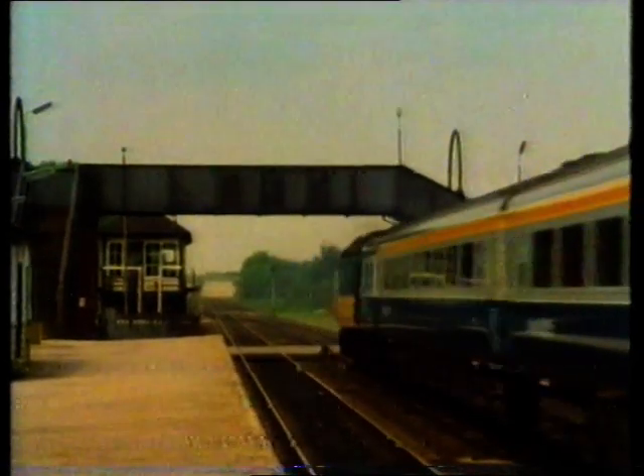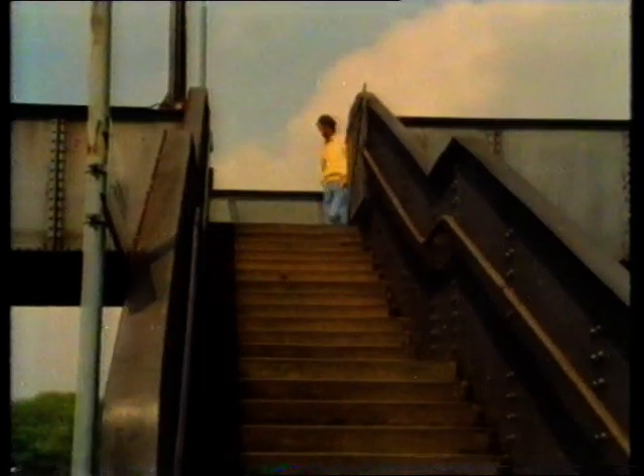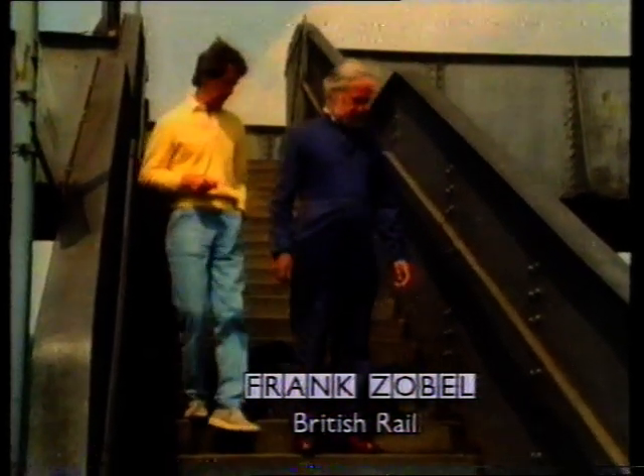And British Rail owns huge numbers of other structures. All are liable to corrode. This is a typical railway footbridge built out of steel. It's very old now. It was built in about 1944. And one of the problems with old structures like this is particularly at the edges where you get dirt accumulating on surfaces, and it holds moisture against the steel, and the moisture gets underneath the edge of the paint. It starts the steel corroding, and the corrosion gradually creeps underneath the paint, pushes it off, and you can see all down these steps the corrosion is quite bad.